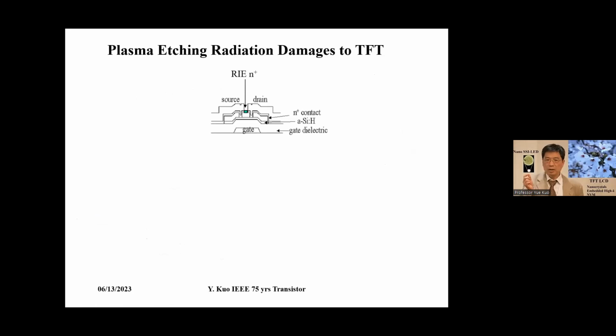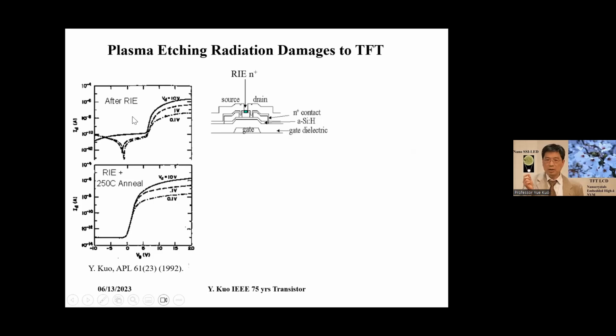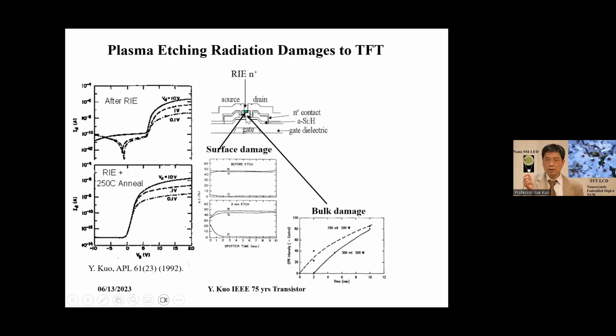Another unique part of plasma etching of TFT is, for example, at the last stage of the N+ layer etch, there is a phenomenon called plasma radiation damage. The transistor after the last step deposition actually has high threshold voltage and high leakage current. It was unknown where this came from and why we had these issues. It became a production problem, an on-off problem, until we clarified that it is caused by radiation damage from plasma etching. This damage can damage the surface, for example the dielectric passivation layer on the channel passivation, and can also cause bulk damage.